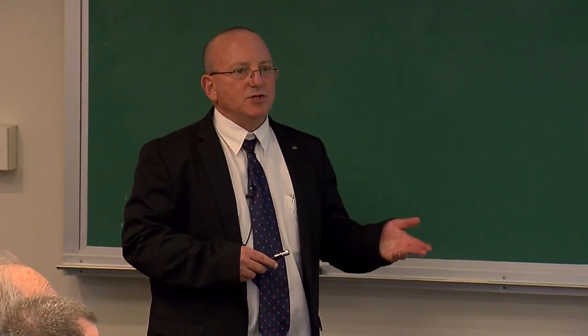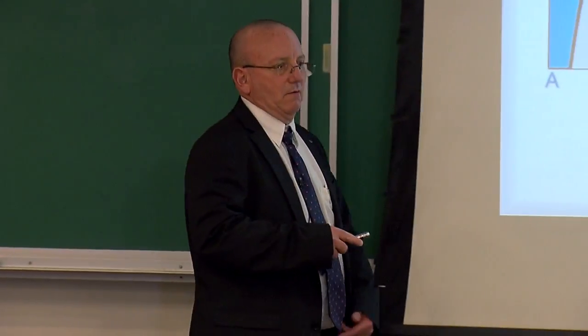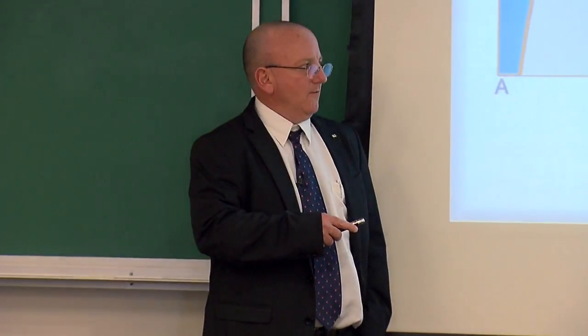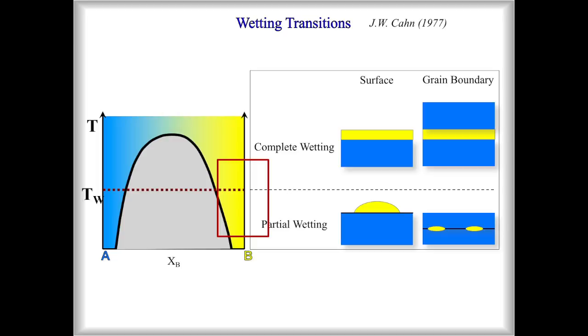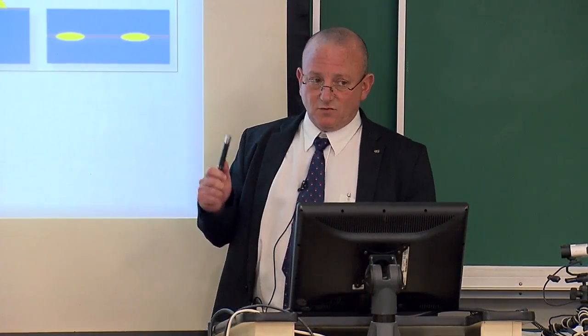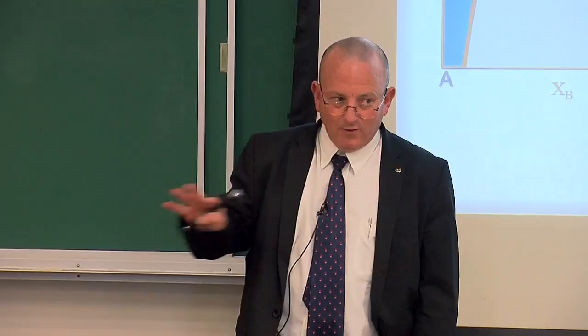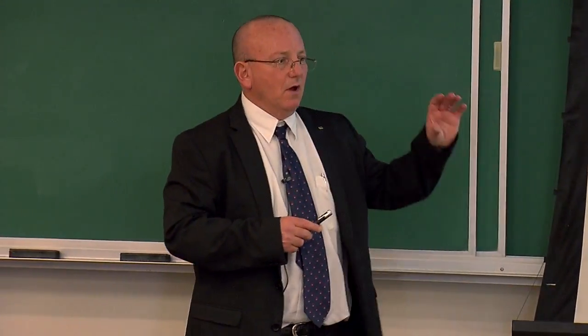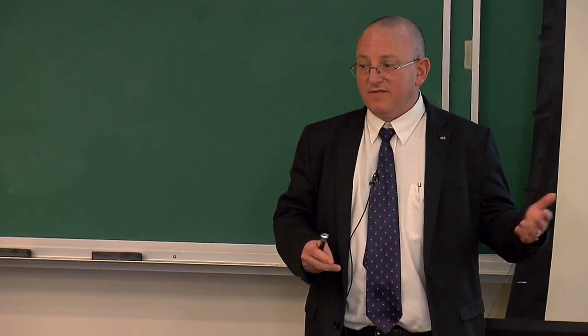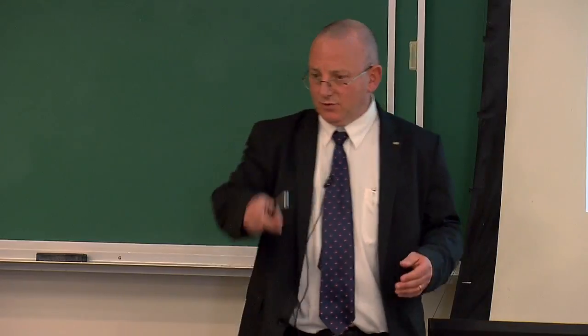So the implications for our microstructure, I kind of drew them out here. We are below, in partial wetting, that was our droplet on our substrate. Now I put them at a grain boundary. So we have droplets or isotropic particles sitting at our grain boundary. Here we have a wetting film. Now this should light off some red lights, because we see wetting films in our material systems all the time, and the transition from separate particles to wetting films is really, really important. By the way, those films at grain boundaries of silicon nitride are not wetting films, okay? So that's not the same thing. When I say wetting, that means that if I add more of that yellow stuff, it's going to get thicker. And those particles will deflocculate. That was your PhD.